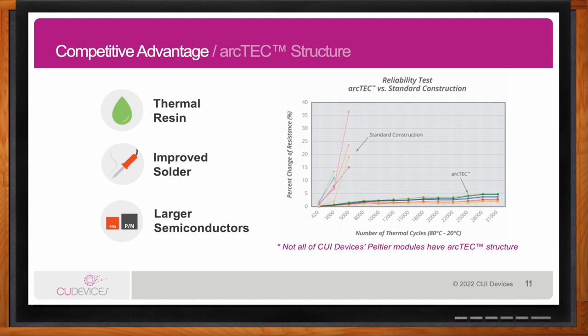One last thing I want to note on this is that not all CUI devices Peltier modules have the arcTEC structure. The main reason is that for very small Peltiers, in general 15 millimeters or smaller, you don't need this feature because the thermal stress, that expansion and contraction, is rather minimal due to the small number of thermocouples inside of the module.